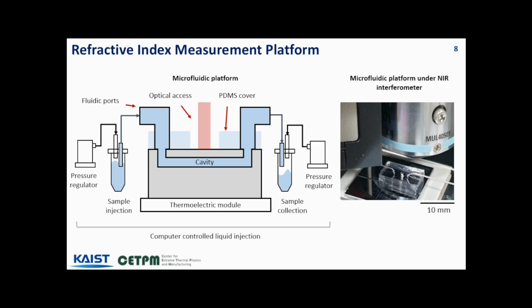We connected fluid ports to the microchannel using a PDMS interface through plasma bonding. To control the flow within the system, we use two electronic pressure regulators that apply differential pressure for pressure-driven flow throughout the entire fluidic setup. The amount of liquid required for the measurement is only in the tens of nanoliters. The bottom of the silicon wafer is maintained at 20 degrees Celsius using a thermoelectric module. The microchannel with a PDMS interface is placed under a near-infrared interferometer, allowing us to measure the refractive index of the liquid inside.